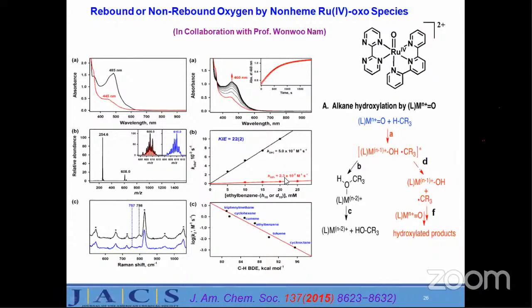And then we thought of doing the reactivity. On addition of a substrate, for example ethylbenzene, the spectrum goes back from this red color to something else, and it gives nice first order kinetics. Based on that we also found the second order rate constant. So this is the reaction on addition of ethylbenzene. And then we compared with deuterated substrates.